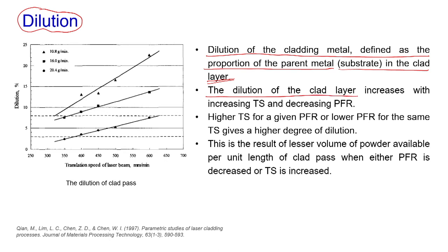So, the dilution of the clad layer increases with increasing TS and decreasing PFR. Here we have taken translation speed on the x axis and the dilution on the y axis, in percentage. Again, we varied the PFR in three levels: 10.8 gram per minute, 16 gram per minute and 20.4 gram per minute. Now, you can notice here the dilution percentage is increasing with TS, that is the scan speed, but it is decreasing with an increase in the PFR. So, if we are putting in more powder feed rate, then the dilution is getting decreased.